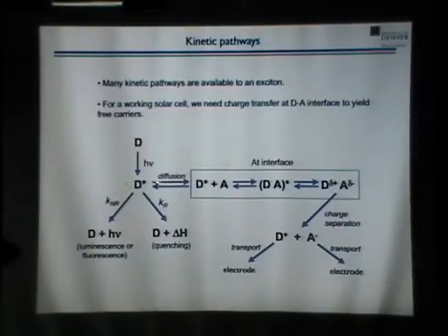What we prefer is diffusion of that exciton to the interface with the acceptor, with the A. So now you've got the exciton sitting right next to the acceptor, and then that ultrafast process occurs, that 45 femtosecond process. Now, there's tons of great physics in here, and as a community, we don't understand all of these steps. There's lots of different theories about what details actually go on here. I'll talk a little bit more about that tomorrow. But we generally agree that what happens is that first, that exciton becomes delocalized across the donor and acceptor. So the electronic configuration spreads over both molecules. And this would happen in a very short time scale, a few femtoseconds.